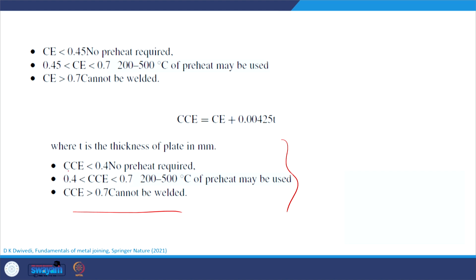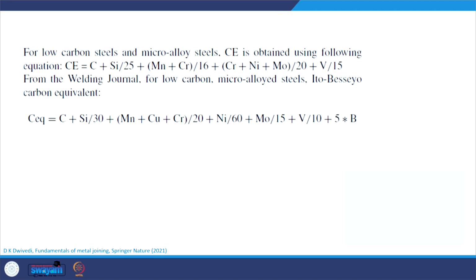So, if the CCE is less than 0.4, then no preheat is required. If the CCE is in the band of 0.4 to 0.7, then preheat of 200 to 500 degree centigrade may be used to avoid the embrittlement and cracking tendency. And if the CCE is greater than 0.7, then the steel is considered to be not weldable, or it requires extra precautions for development of the weld.